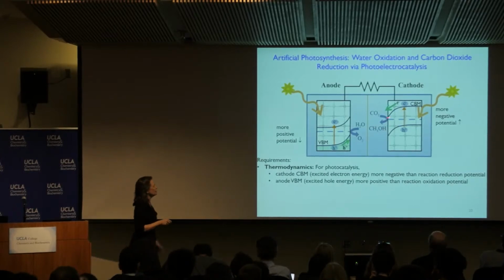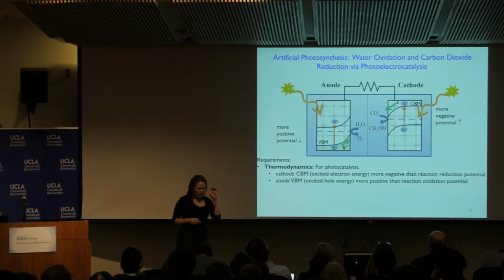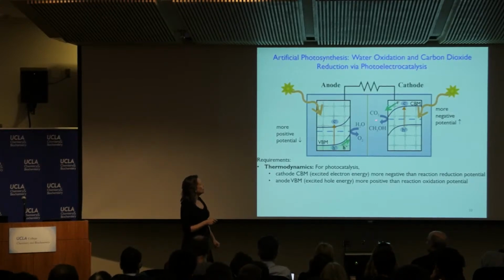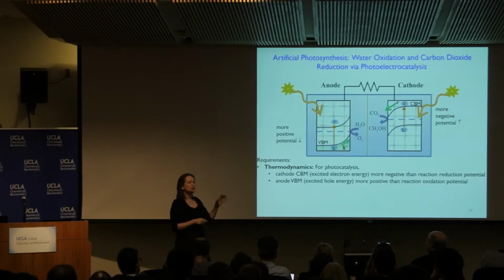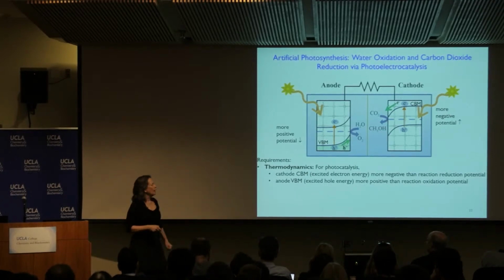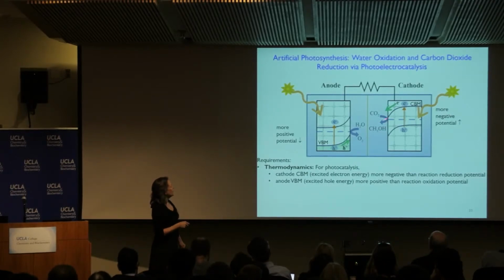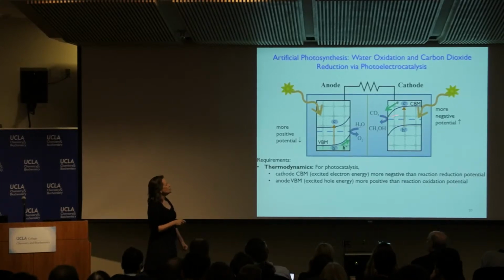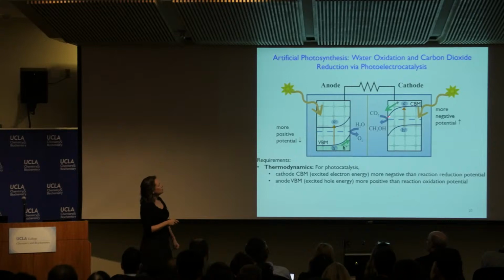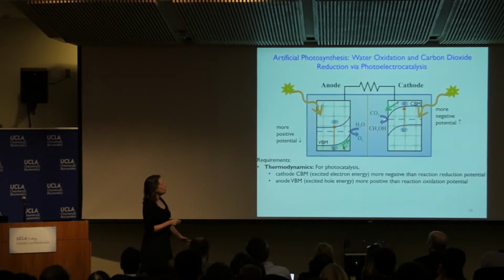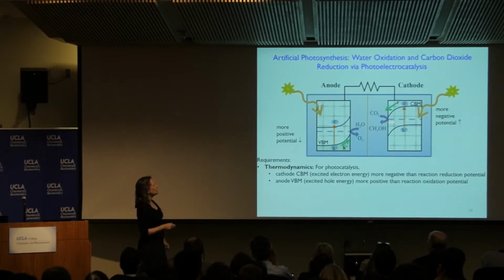So what we're going to see on a slide is the results of a lot of work that show how we can calculate these conduction band edges in the presence of water in order to then compare them to these reduction potentials on the same scale. And so we want to make sure that the energy that's right here at this interface is larger, more negative than the reduction potential of whatever reaction we're looking at.